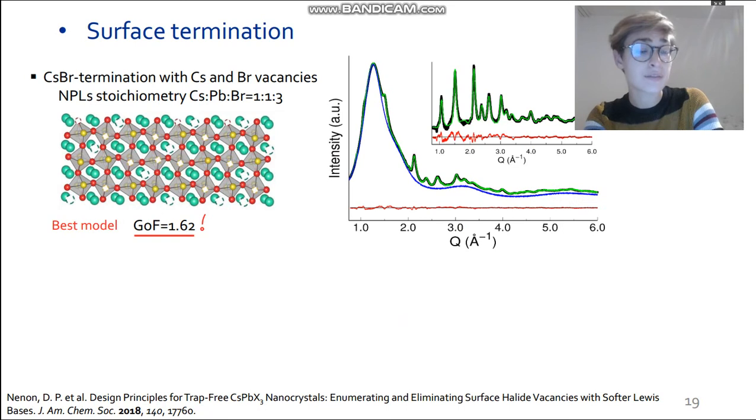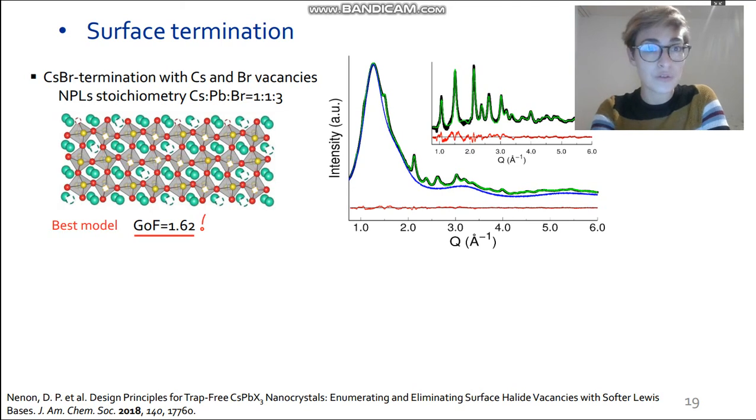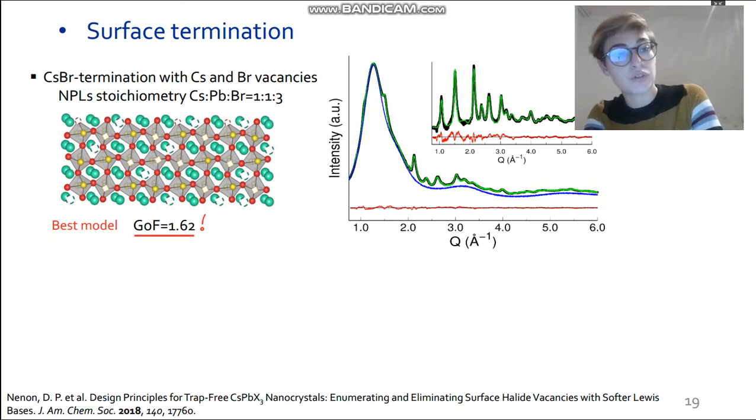Despite the fact that the X-ray diffraction technique is not devoted to surface analysis, total scattering methods can become sensitive to superficial features when samples have a high surface-to-volume ratio, which is especially true for plate-like nanocrystals. And in order to investigate the termination of cesium-lead bromide nanoplatelet surfaces, the best atomistic and morphological model was used, considering for it three alternative surface descriptions.